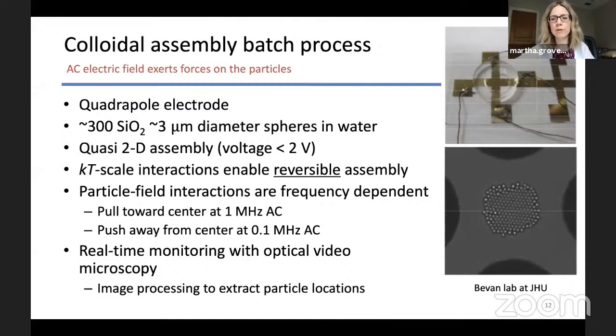So this is work with Michael Bevan's lab at Johns Hopkins University in chemical engineering. The experiments are all done there. And in the work I'll show today, we have about 300 micron-sized silicon dioxide particles in water. So they're solid particles suspended in water. And we only apply voltage to generate an electric field that moves the particles around. That's our manipulated variable. But we only apply high enough field. We constrain the field so that the particles don't buckle into 3D. So we only have a two-dimensional crystal here.